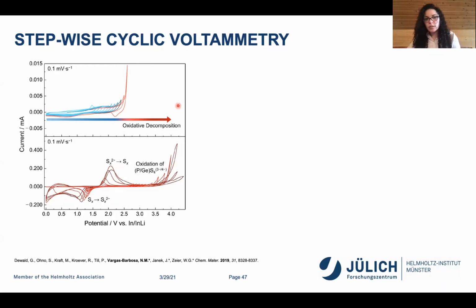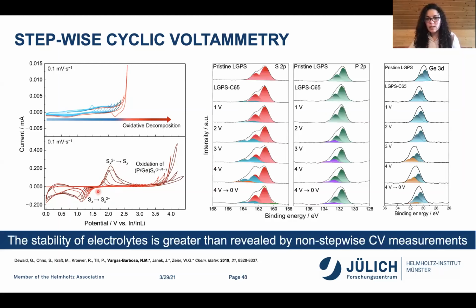And then you keep pushing the oxidative potential, and you start getting all sorts of crazy peaks here. It was only then, with the help of XPS, that we were able to tell that these redox peaks are actually associated with the redox chemistry of the decomposed PS4 and GeS4 tetrahedra. This is very important to clarify, because in the first CV, it almost looked like our material itself was redox active.